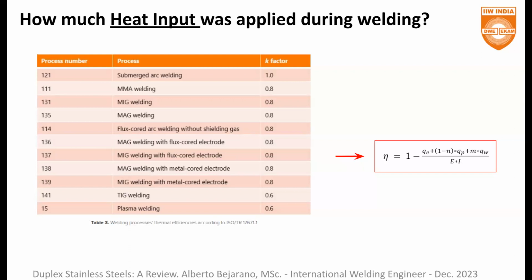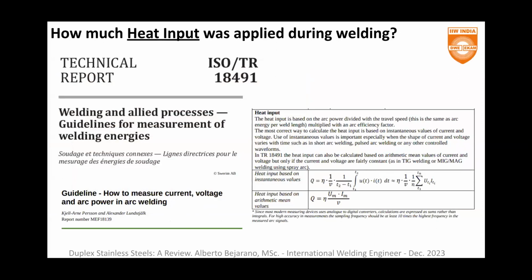If you see, for instance, TIG welding is only able to take 60% of all the power in the arc and carry that power to the base metal. So we lose 40% of the original heat input, which means that at the end we need more power. And I will show you why this is so important. So, real values for heat input use the K factor, having in mind the technology of your machine.